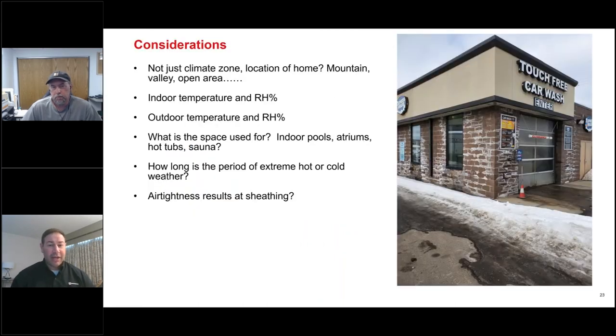This is a great picture from Randy showing vapor drive through a block wall — in this case a car wash. The vapor drive, summer or winter time, moves through a block wall, grabs the salts and the stuff in the concrete blocks, and ends up on the exterior of the building. Underneath the windows, the grout joints are pretty much gone — they've all deteriorated. That's presumably from a freeze-thaw cycle where temperatures don't get above freezing for three to four months sometimes. The high moisture content in those blocks combined with the freeze-thaw cycle is very damaging. And the reason it's such high moisture content? It's a car wash — there's a hundred percent humidity at times inside the structure trying to get to that drier outside air and moving through the blocks.